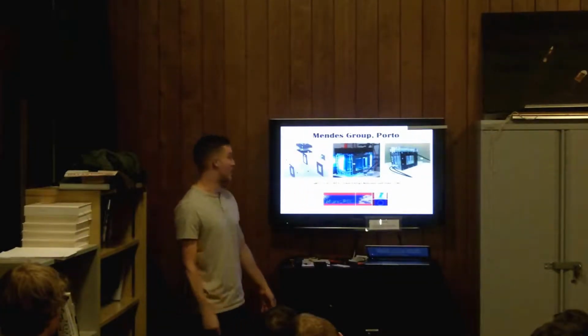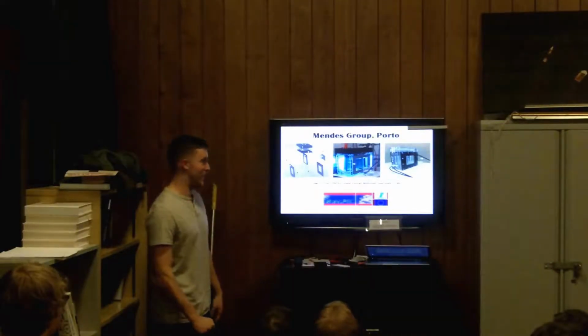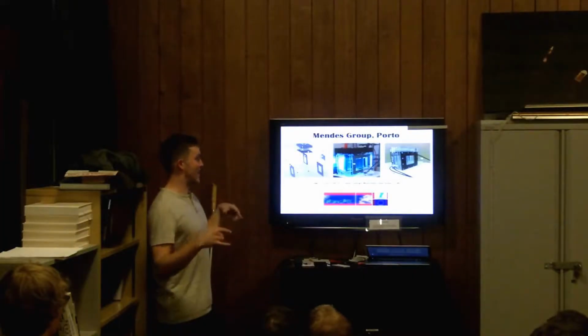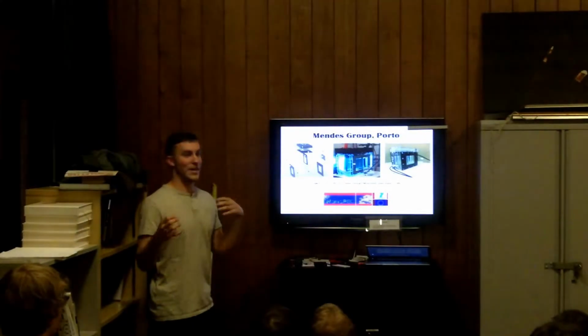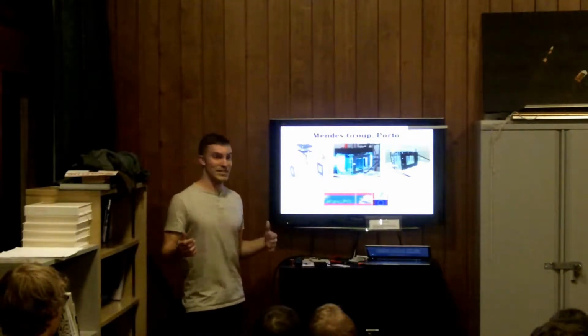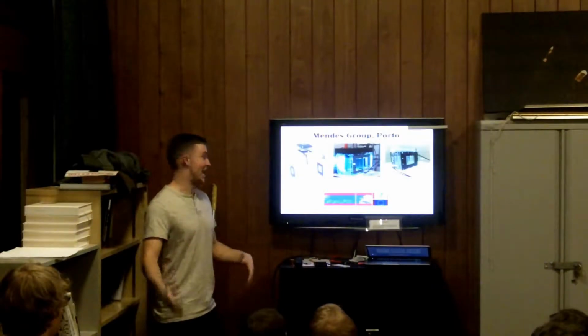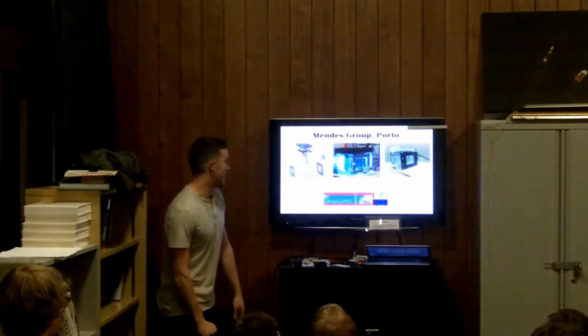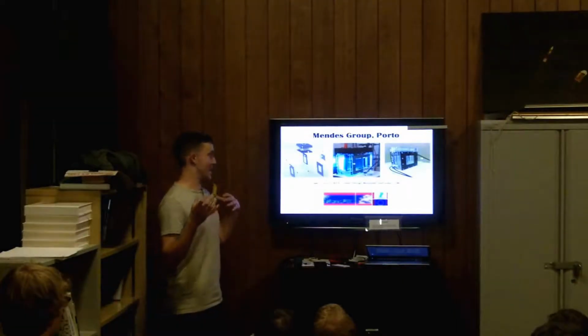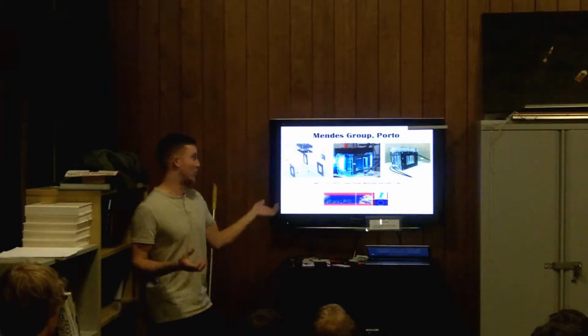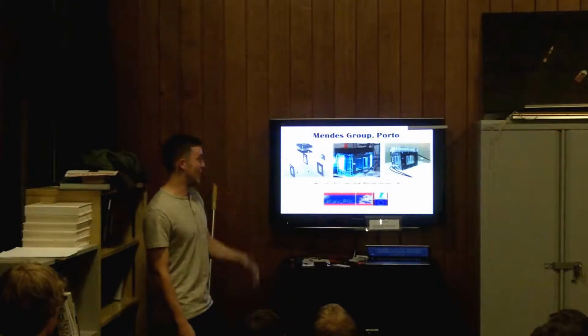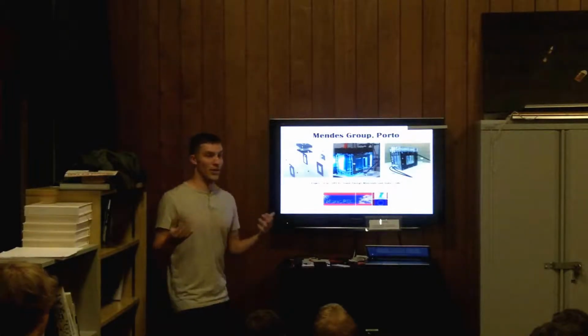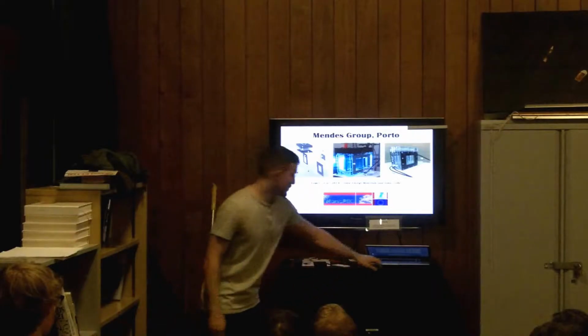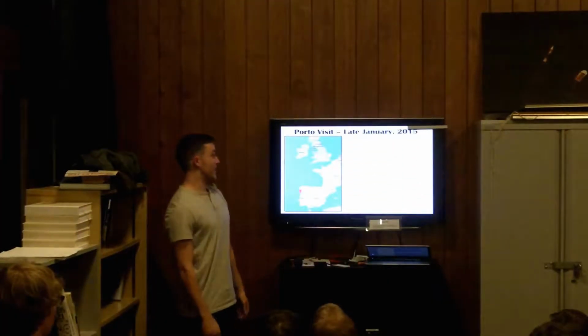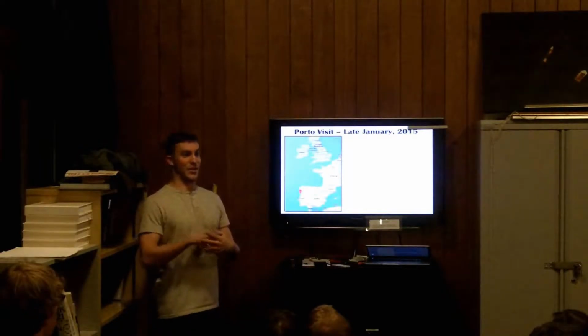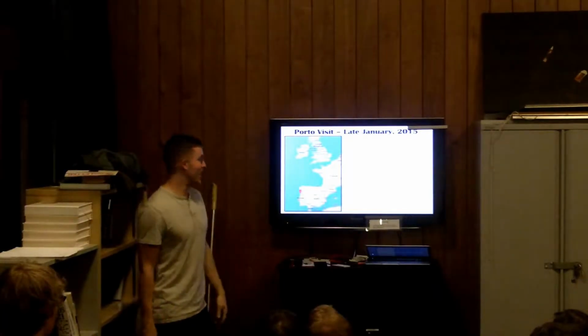So I stumbled upon this reactor here. It looks really futuristic, and it's on a 10 by 10 centimeter scale, which doesn't sound that big, but compared to the scale that we work at right now, which is usually 1 centimeter by 1 centimeter, this is about 100 times the area of what we're currently working with. And so I found this group in Portugal that has been working on a project to develop something that looks like a commercial product that they can market to other laboratories, and that gives you a more rigorous testing ground for your materials. And so I've started a collaboration with this group in Portugal because it seems like they're really leading the world in terms of these devices that they're producing.